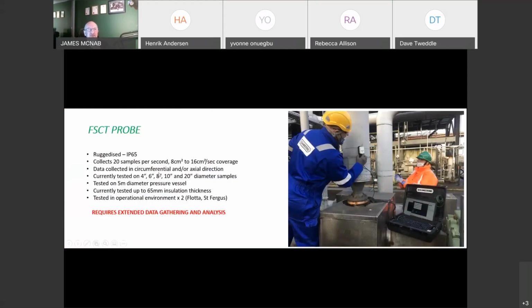It's ruggedized IP65. It collects 20 samples per second, is what we've estimated, and that's the kind of coverage area. The data is collected in the circumferential and/or axial direction. We're actually thinking that the axial direction seems to be a better way of collecting the data.